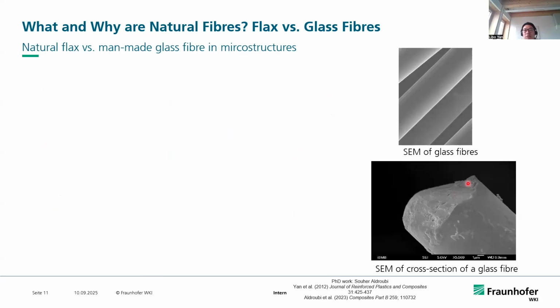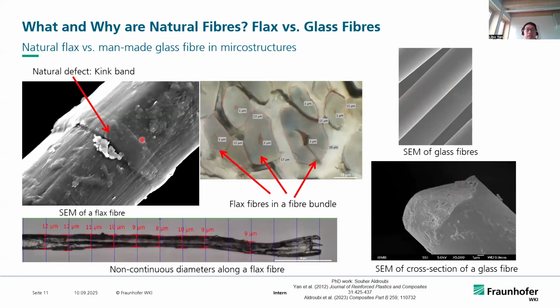So how about the comparison of the microstructure between the flax fiber and the glass fiber? Let's take a look. The glass fibers have a very unique structure. You can see a very smooth surface, and the diameter is quite constant along the length. But the plant-based natural fibers, like flax fiber, show high variation. You can see the existence of natural defects, like the kink bands, and the varying diameters along a flax fiber. And you also see the irregular cross-section of the individual fibers.